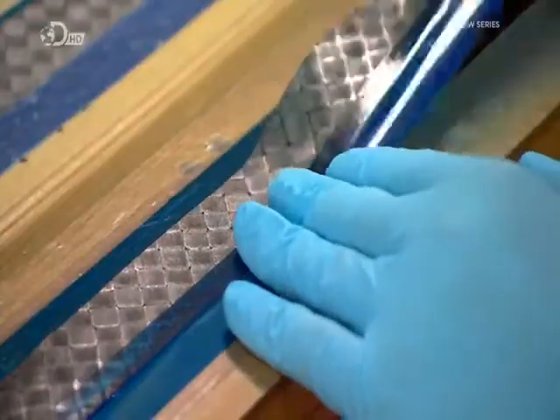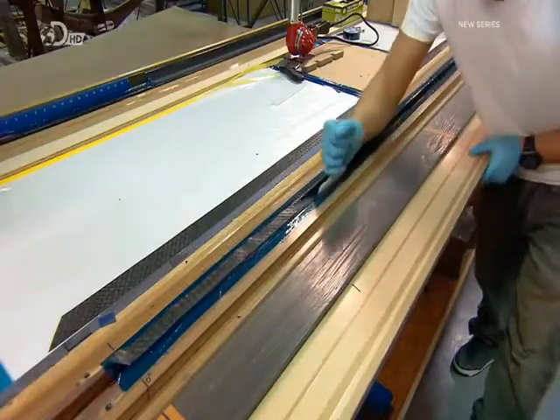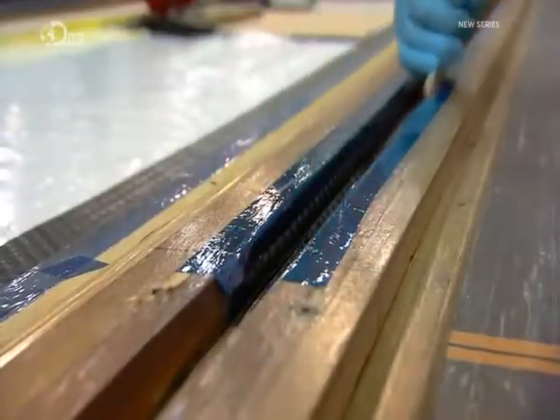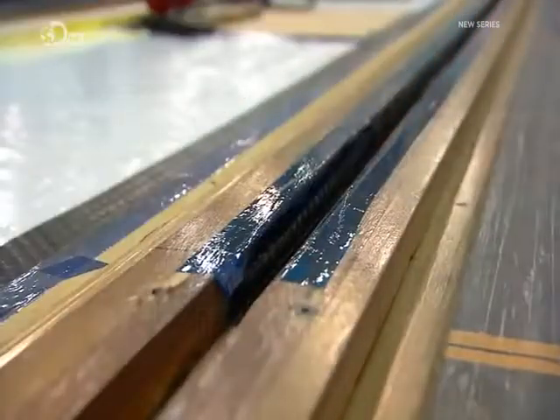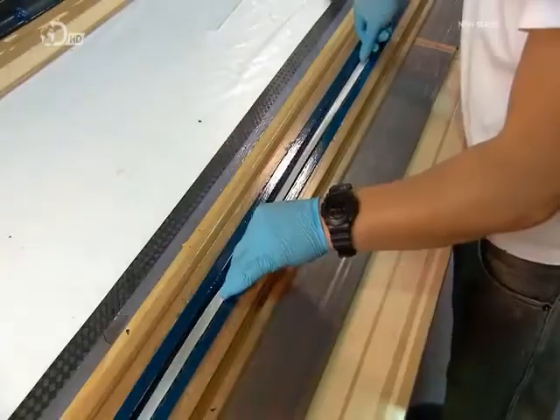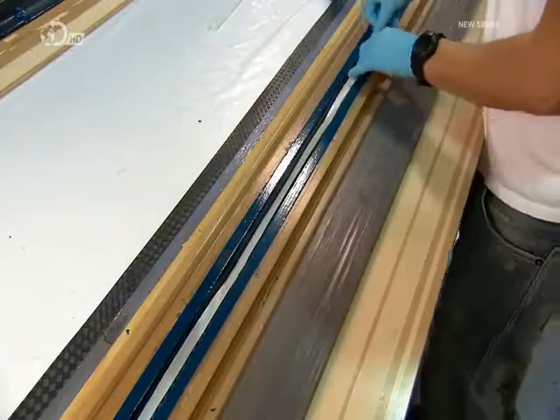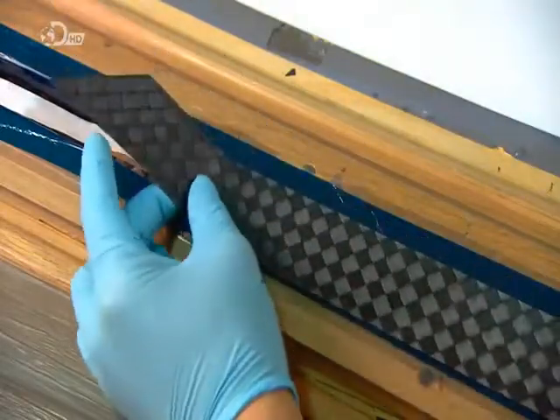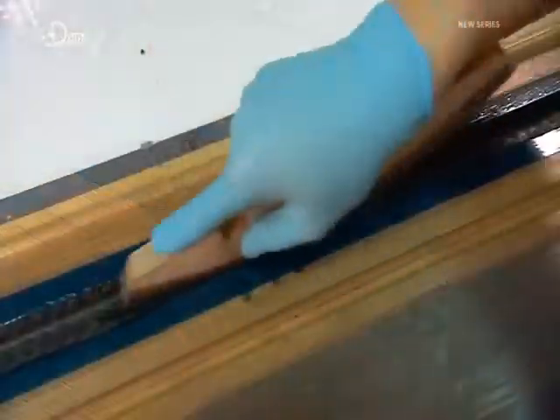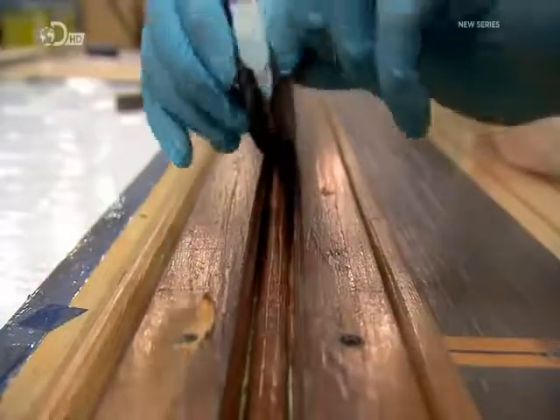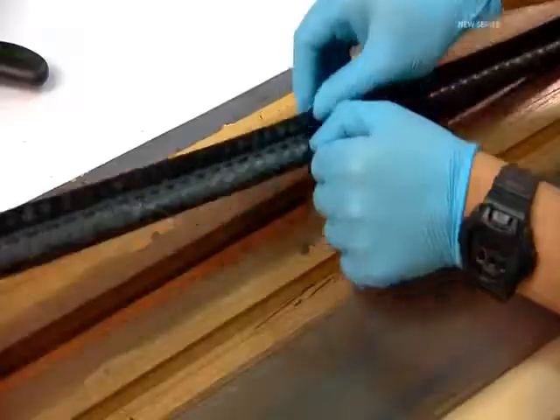A colleague layers material for the wheel rims by inserting strips of carbon fibre into a long and narrow mould and pushing it into the crevices. He applies strips of carbon to the sides for reinforcement. A resin-based film adhesive is added, followed by more carbon fibre. Using a wedge, he again puts on the pressure, causing the carbon fibre and film adhesive to stick together.